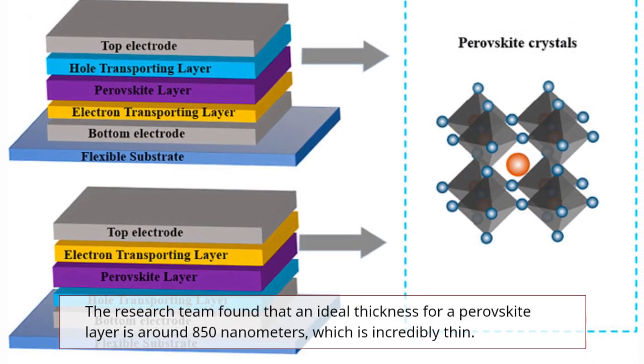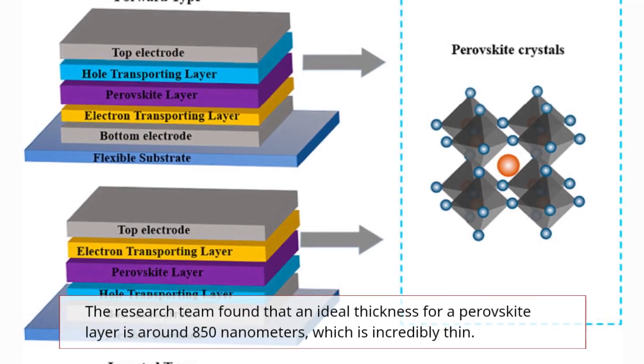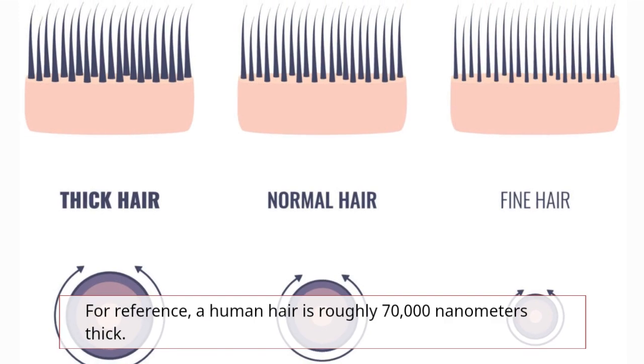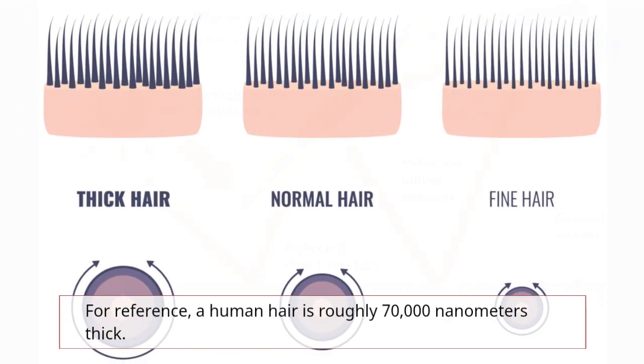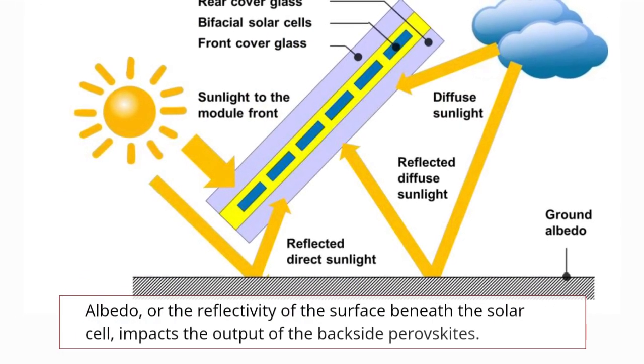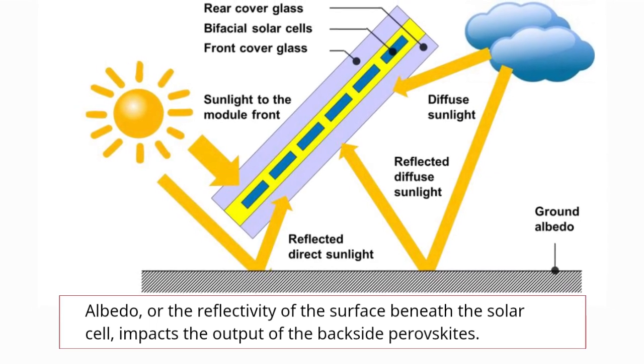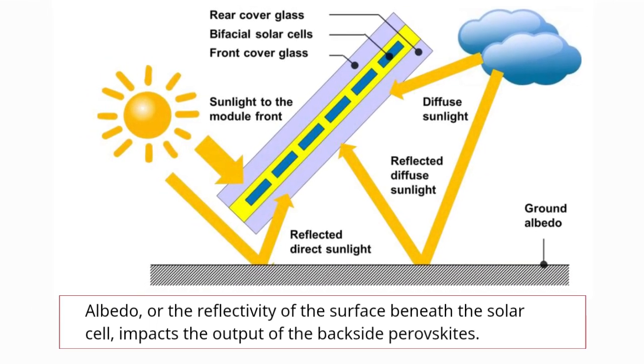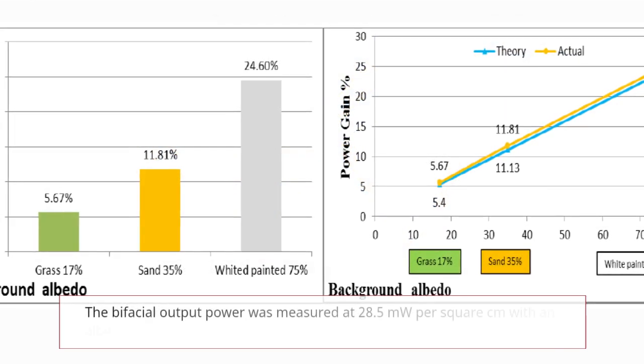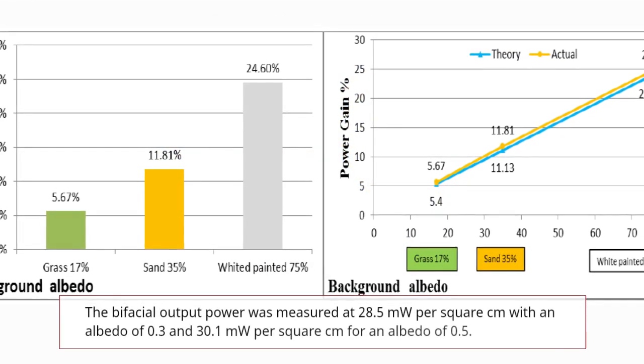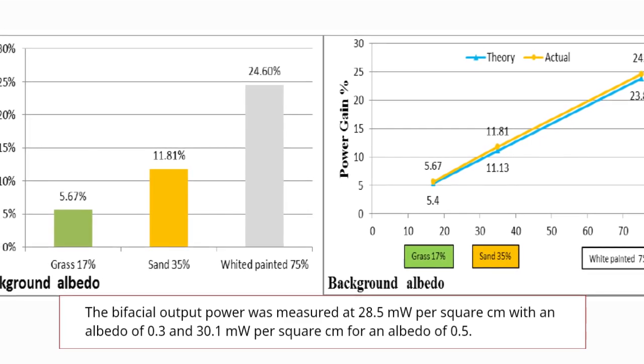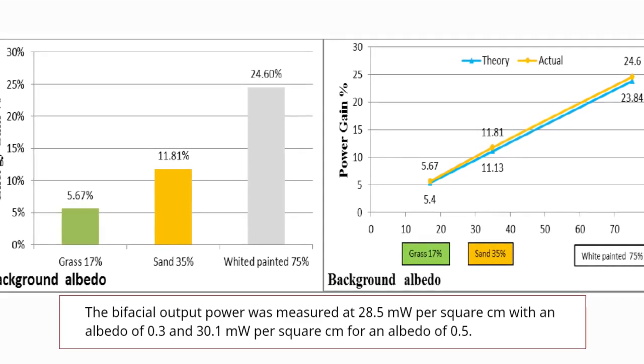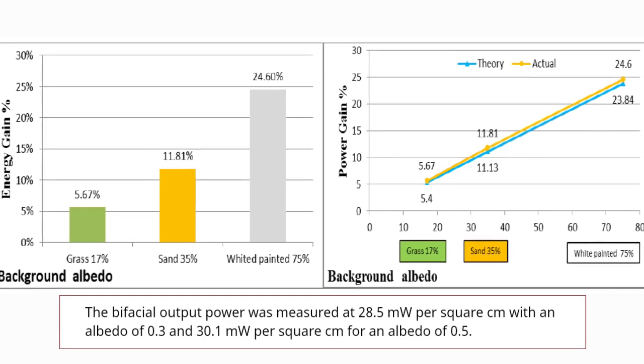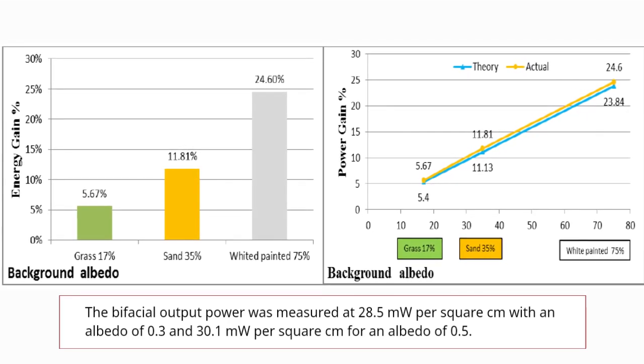The research team found that an ideal thickness for a perovskite layer is around 850 nanometers, which is incredibly thin. And for your reference, a human hair is roughly 70,000 nanometers thick. The albedo, or the reflectivity of the surface beneath the solar cells, impacts the output of the backside perovskites. As a result, the bifacial output power was measured at 28.5 milliwatts per square centimeter with an albedo of 0.3, and 30.1 milliwatts per square centimeter for an albedo of 0.5.